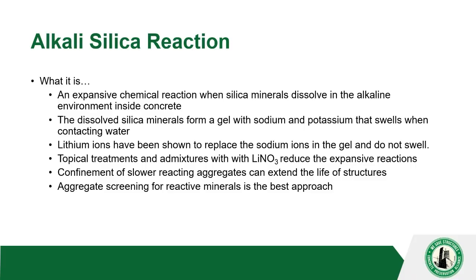So rain would come in and sit in that sand and then keep that concrete wet. And alkali silica reaction expands with water. So that triggered the reaction, and the entire length of that parking garage that had the brick paver depression had to be revamped. They had to pull the pavers out and recast concrete in that area and make it drain away from that area. And they had to treat the beams with lithium nitrate.